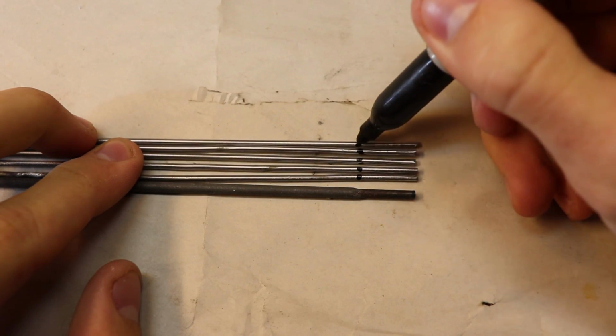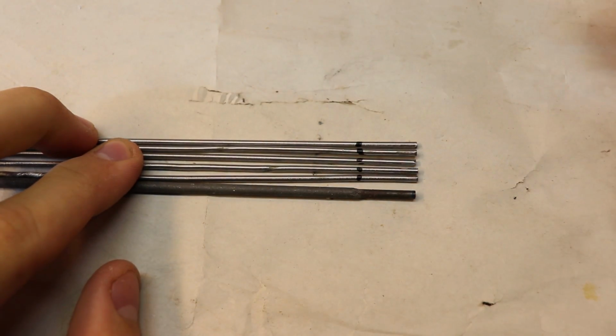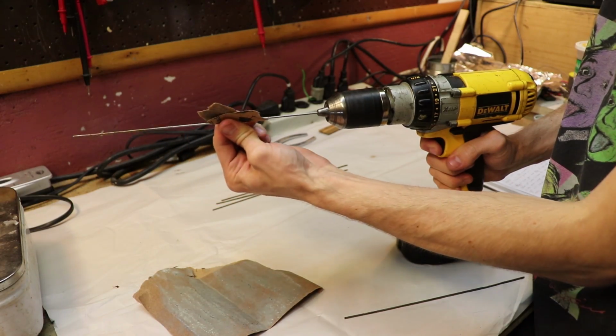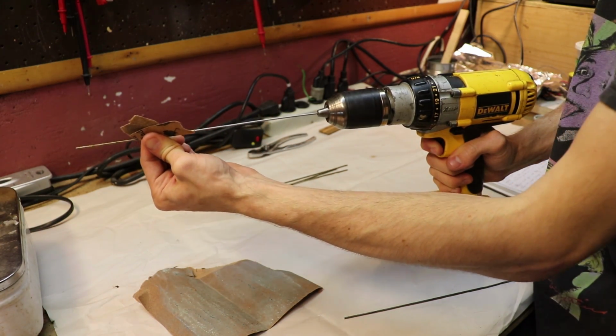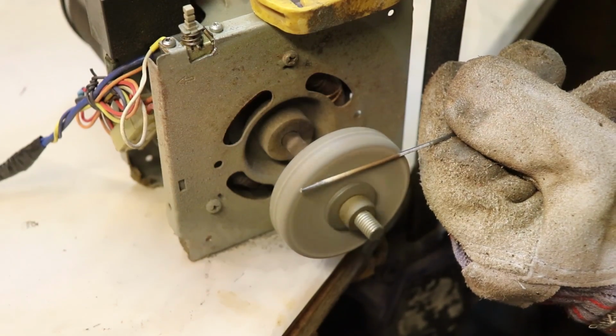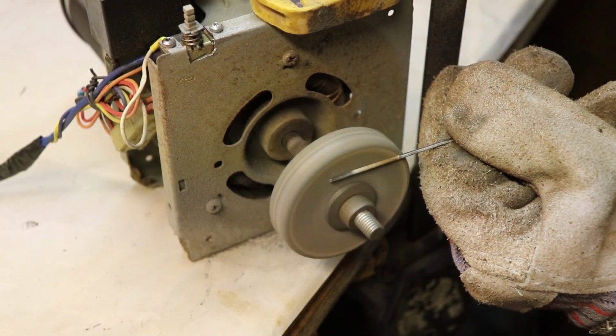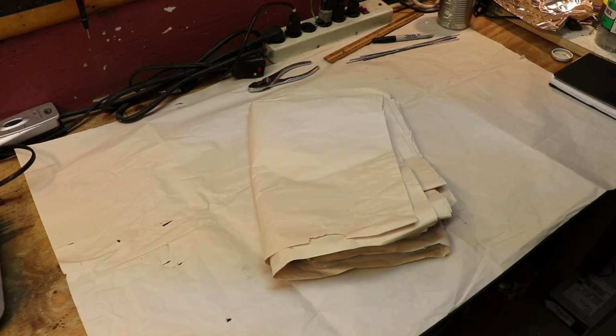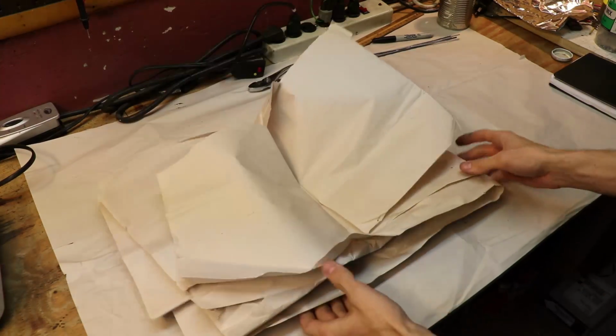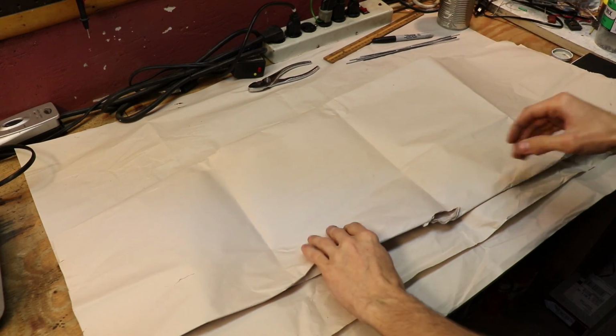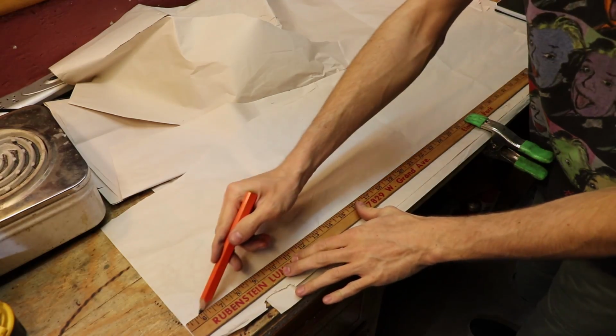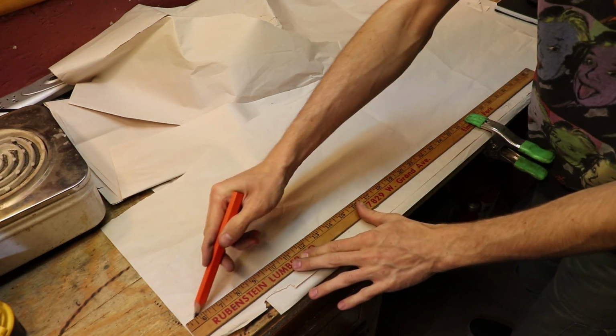I also marked about 1/2 inch of space at the very end of each rod too, and got rid of the coating by using my drill and some sandpaper, and when that wasn't enough, I used a bench grinder instead of sandpaper. Now to wrap these rods, I'm using this paper that was used in a newspaper printing factory. These are nice because they are long and I can cut long strips from them.